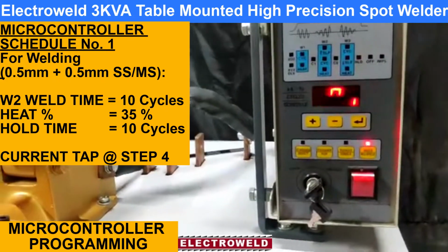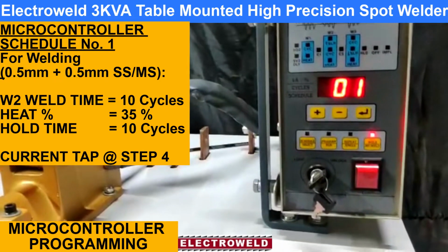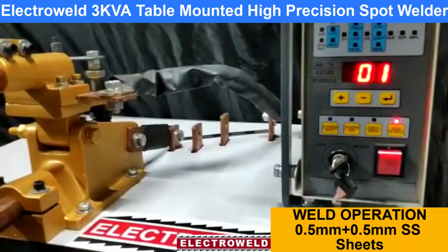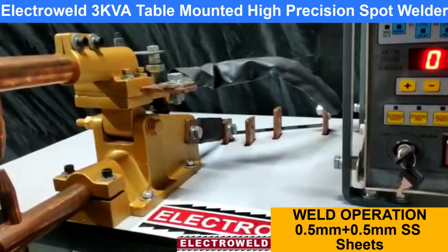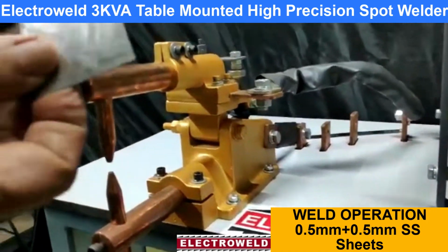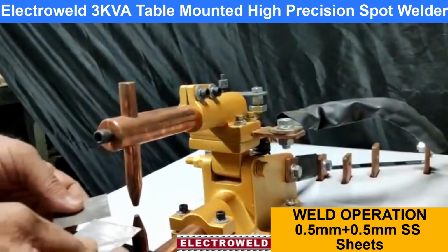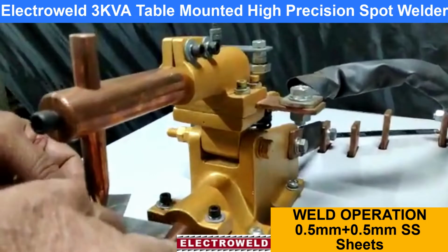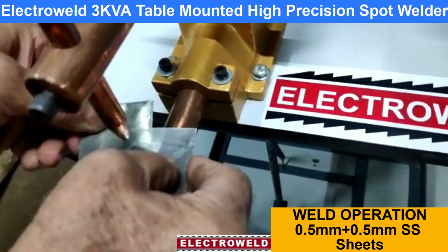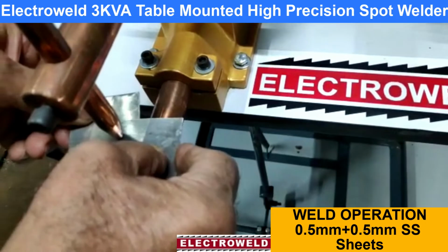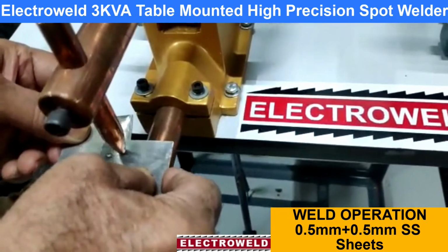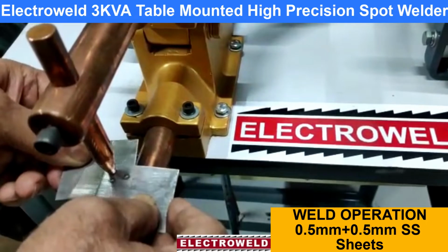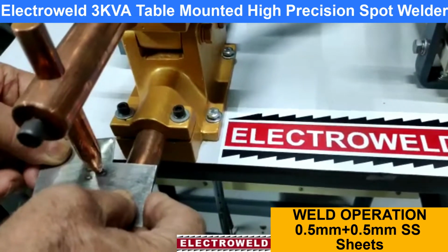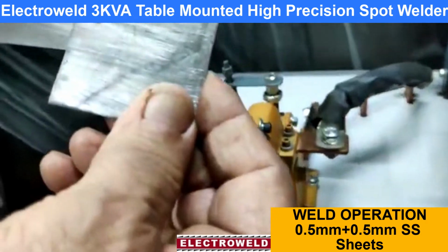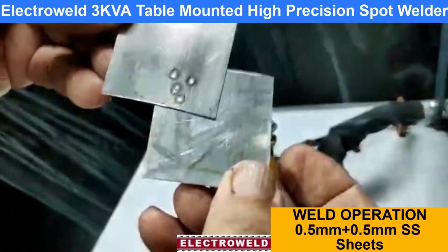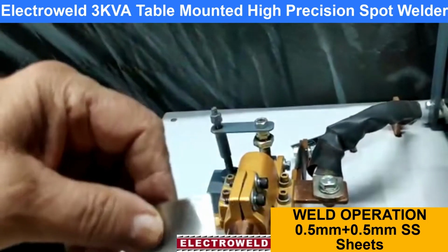We will show you the welding of 0.5 plus 0.5 thick components. So this is a 0.5 plus 0.5 SS component. You can keep the two pieces in between the electrodes. Press the pedal. You will see welding taking place. This is how the welding takes place. So this is how it's welded. And this will not break.